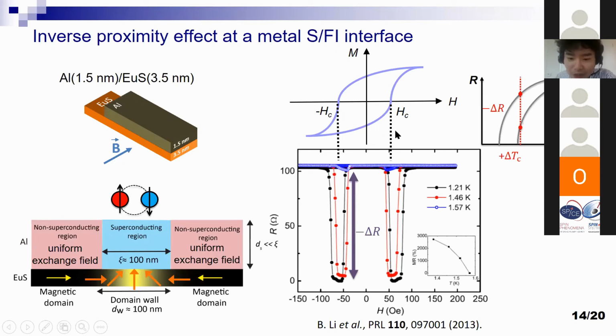And they measured RH at around the onset superconducting transition temperature. And they observed the drop of resistance. Drop of resistance means increase in TC because they are measuring around the superconducting transition. So they observed increase in TC at the point where the domain wall density is maximized, so around the coercive field.